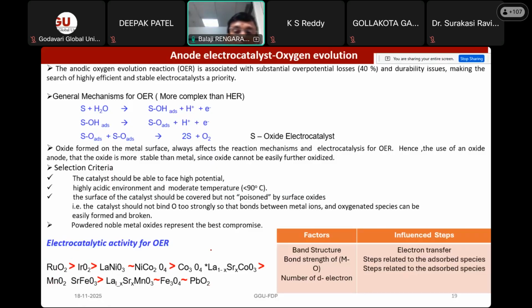But the basic idea in the selection of material is that when you take any metal which is used as an electrocatalyst for the oxygen evolution, obviously when you use it as a positive electrode, the metal will try to get oxidized into metal oxides. That is the nature of any metal. So the energy you spend is mostly utilized to convert the metal into metal oxide instead of water into oxygen. So you have to be careful in choosing a material which is already in oxidized form, for example ruthenium oxide or iridium oxide. Then whatever energy you give for the oxygen evolution is directly used to generate oxygen from the water. That is the logic behind the selection of the material.